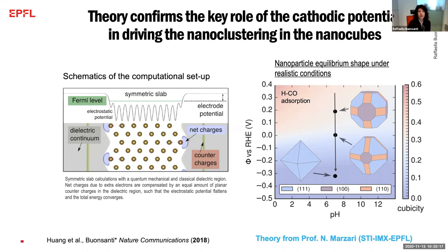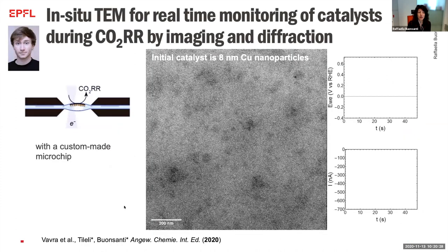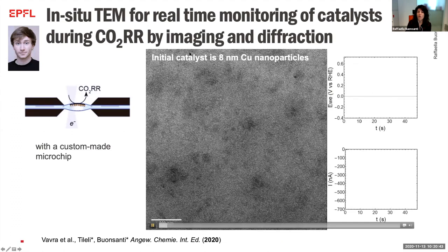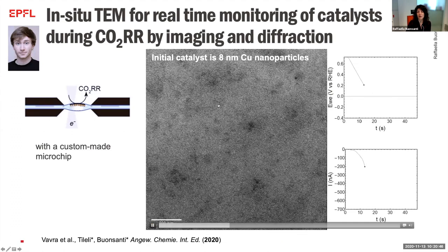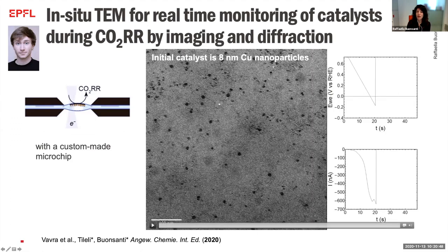Now, for this work, what Jianfeng did were ex situ imaging of the catalyst. So we wanted to go a step further, and in collaboration, my student Jan, with my colleague Vaso Tileli, we started to develop a custom-made setup to look at catalysts while they are functioning. So what I'm showing you here is a video of initially 8 nanometer copper nanoparticles as they evolve during the reaction. So we can apply the potential and run the CO2 reduction and observe the catalyst while it's changing.